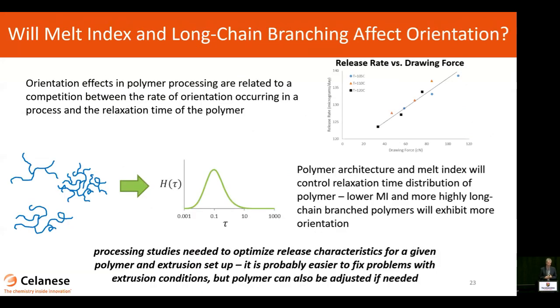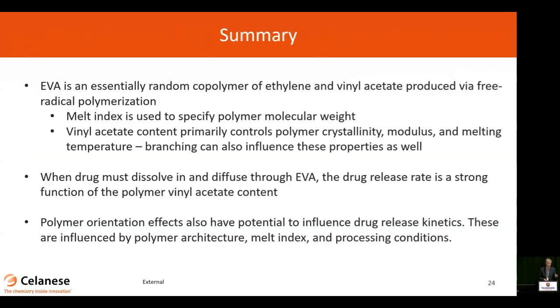Well, this is where the long chain branching and melt index and rheological measurements could impact drug release, right? We said initially vinyl acetate content and crystallinity is the primary effect here, but because you do have potential to have orientational effects, if you had very, very different polymer architectures and you put them through the exact same process, you might end up in a situation where you have different drug release characteristics as well. Now, you can probably fix that on the back end by adjusting processing parameters, right? And no two processes will be exactly the same. So there will always be some work to optimize this and dial in the release characteristics based on processing parameters. But this is an aspect of the polymer that's going to play a role in that.